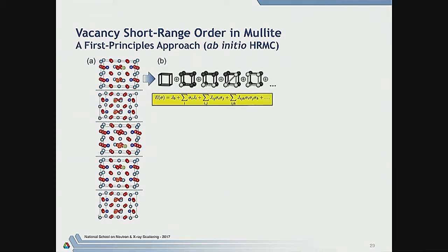And from that, he was then able to produce a kind of pseudo-Ising-like Hamiltonian, which is a cluster expansion, basically, which says, okay, if we have two vacancies together, then that's going to be characterized by this Jij. If we have, for instance, a tri-cluster, then there'll be this Jijk. So you can generate this cluster expansion, which basically means you've collapsed that whole ab initio calculation onto a small set of numbers, which do reproduce the energies of larger clusters.